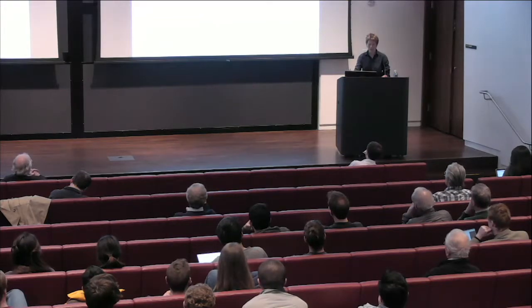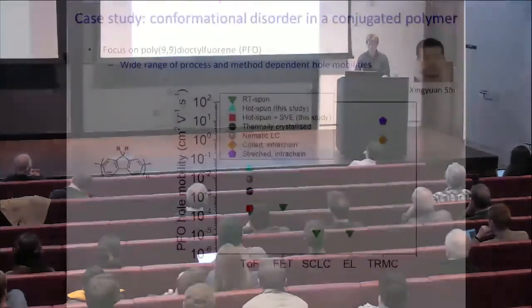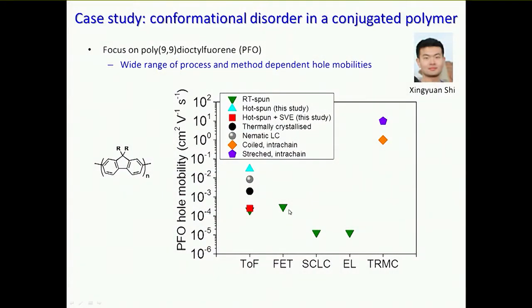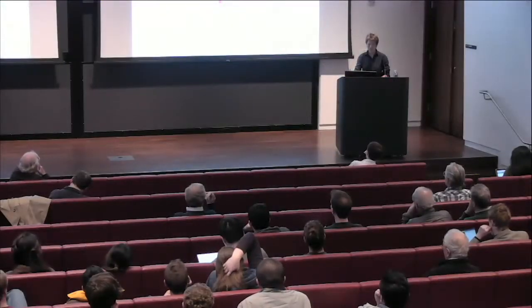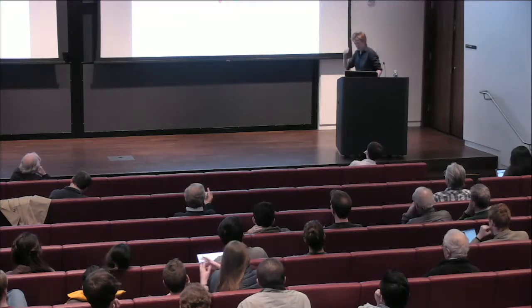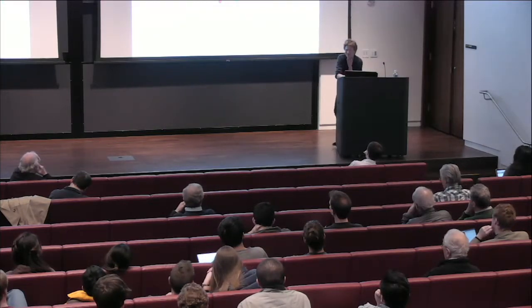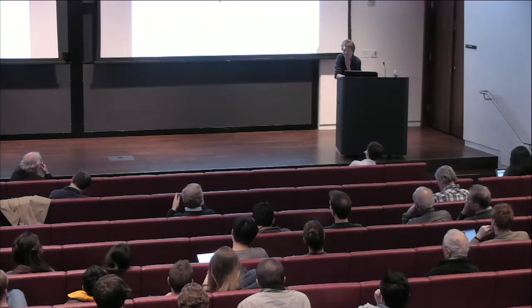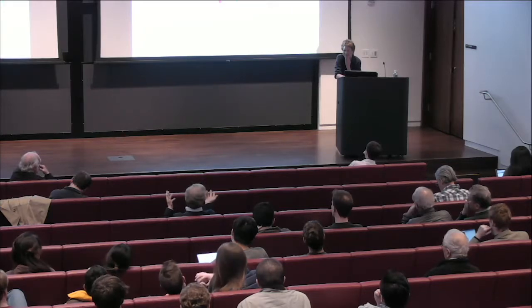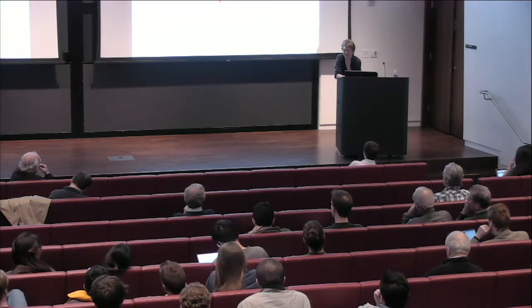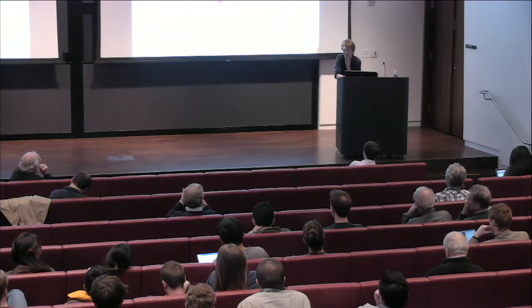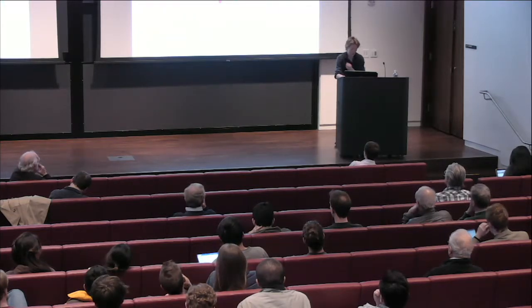Was there a TFT? Yeah, they're probably in the very first one here. And FETs, yes. That mobility is quite low, whereas one would expect that technique to give you generally a higher mobility. In particular, with this normal trap, you would expect the traps to be filled in the field effect transistor above threshold and so on. So, do I understand that wrong? No, I mean, I think, so